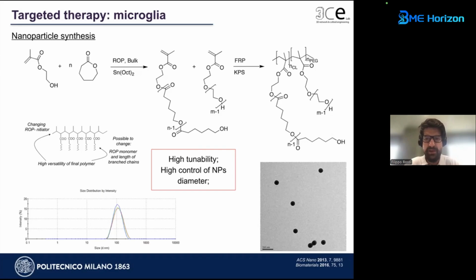Then with free radical polymerization, we can obtain, as you can see on the top right, the skeleton of the polymer. This polymer presents a hydrophobic chain and a hydrophilic one; it is a comb-like polymer, as you see from the picture in the middle, and due to this amphiphilic nature, once nanoprecipitated in water, they create nanoparticles that self-assemble, with dimensions of about 100 nanometers in this case. What is important here is that by tuning the amount of caprolactone, we can tune the dimension of the nanoparticle, and in particular by increasing N, we can reduce the dimension of the nanoparticle because we increase the hydrophobicity of the system. In this case, 100 nanometers is good for us. We are not very strict about the dimension.